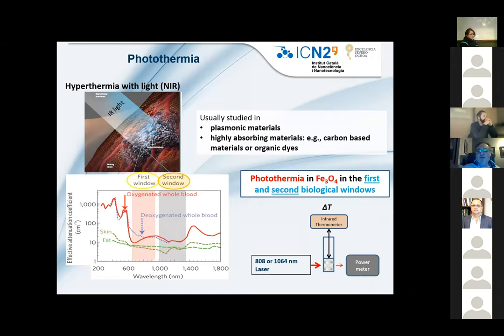But as I mentioned before, Fe3O4 can also be used with infrared light. Usually optical hyperthermia, or what's called photothermia, is done using plasmonic materials or highly absorbing materials like carbon-based materials or organic dyes. And why do we want to use near-infrared light? This is because in this range, about 700 to 1,300 nanometers or so, the water and the tissues in the body absorb the least amount of energy. So that means that the light can penetrate much deeper using this near-infrared region.